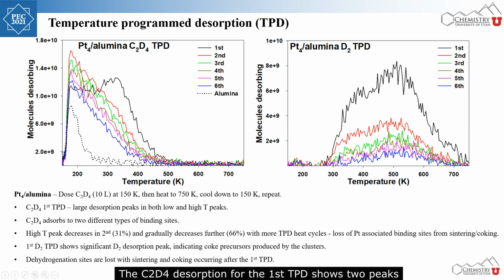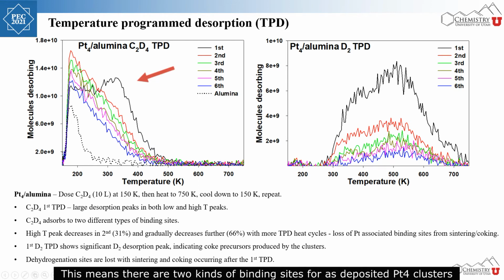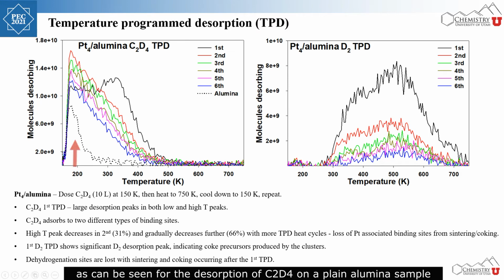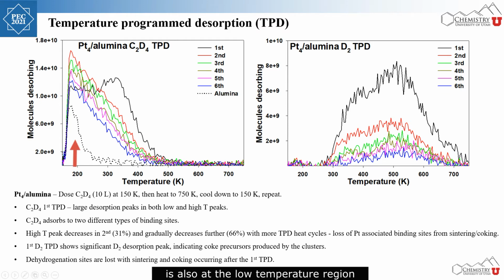The C2D4 desorption for the first TPD shows 2 peaks, a low temperature peak and a high temperature peak. This means that there are 2 kinds of binding sites for as-deposited platinum-4 clusters. The high temperature peak is associated with binding sites on top of the platinum clusters, while the low temperature peak is associated with the alumina support, as can be seen from the desorption of C2D4 on a plain alumina sample here, which is also at the low temperature region.